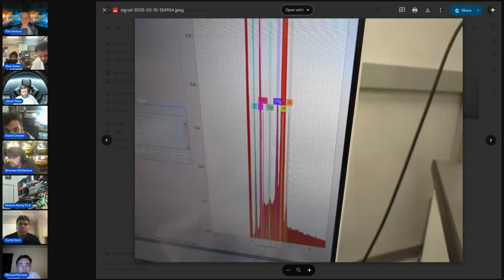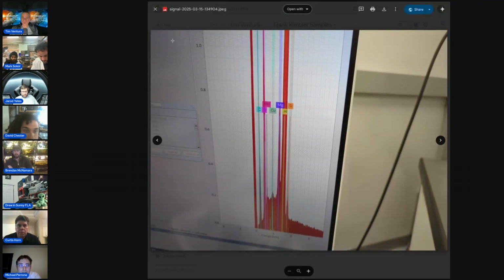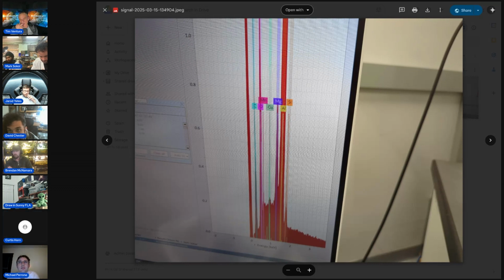So our initial, very, very preliminary data, it looks like there's some manganese. Maybe there's a little bit of copper. And then magnesium, aluminum, and silicon, which is fairly standard for a 7000 series aluminum. There's copper and oxygen there too. We suspect maybe the copper and oxygen are from the epoxy surrounding it. If it was really charging up severely, it would have been bouncing electrons back into the detector, even though it wasn't in the field of view. So yeah, I suspect that might have been the case, but we'll see. We'll see what we can do about that tomorrow.